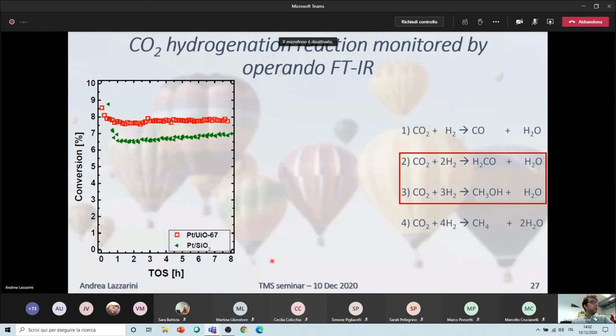To do so, we were testing both the platinum MOF system and the platinum silica system. And as you can see, the platinum MOF, after activation and forming nanoparticles with a size of almost 2 nanometers, was a bit more active than the traditional platinum on silica system, meaning that the MOF somehow can have some impact on the catalysis. But unluckily, what we were doing was just reaction number 1. So we were producing carbon monoxide from carbon dioxide, so not a very interesting system for this kind of reaction.